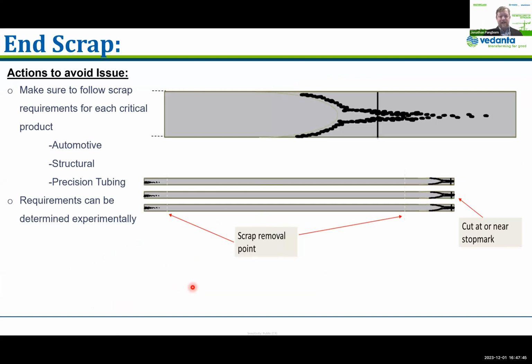If you cut on the stop mark, it's going to look like this, where you have a transverse weld, which is difficult to see in this graphic. I don't know if you can see that. And then you have inflow, and then it's proceeding into the front of the previous billet, which is actually the back of the previous billet, which is showing the back end of the runouts. So understanding how much scrap you have to take and following that is extremely important when it comes to these type of products. I mentioned some of these type of products before. There can be others as well.